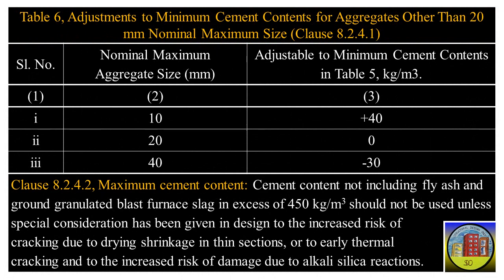On this slide, you'll encounter Table 6, which details adjustments to minimum cement contents for aggregates other than 20 mm nominal maximum size, as per Clause 8.2.4.1. Additionally, Clause 8.2.4.2 addresses maximum cement content. Table 6 consists of 3 columns and 3 rows. The first column functions as a serial number identifier. In the second column, the nominal maximum aggregate size is specified in millimeters. Transitioning to the third column, it pertains to the adjustments to minimum cement contents as outlined in Table 5, expressed in kilograms per cubic meter.